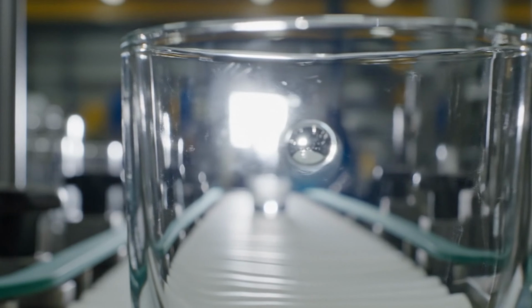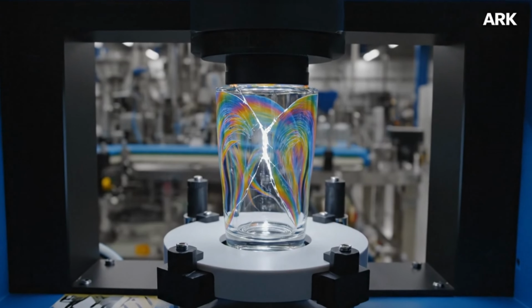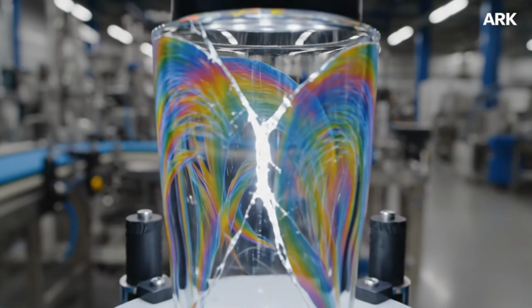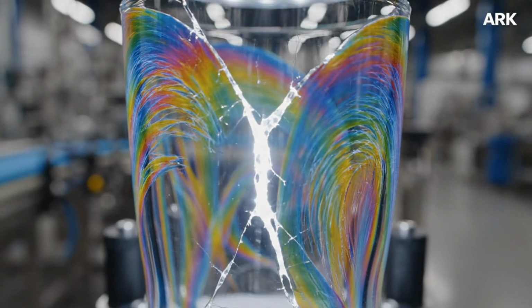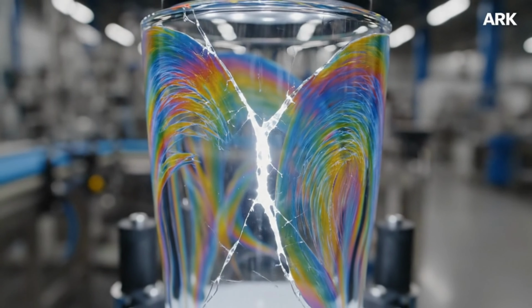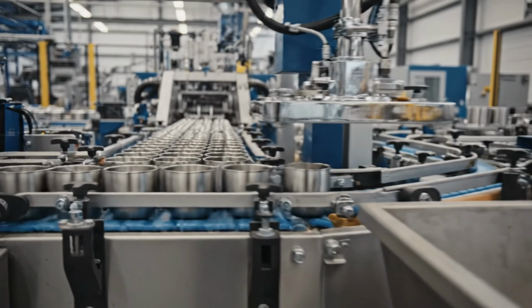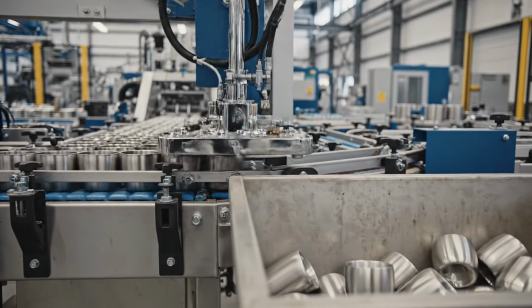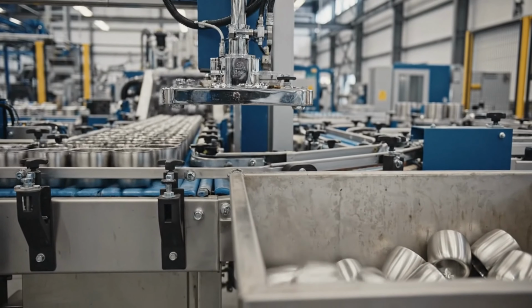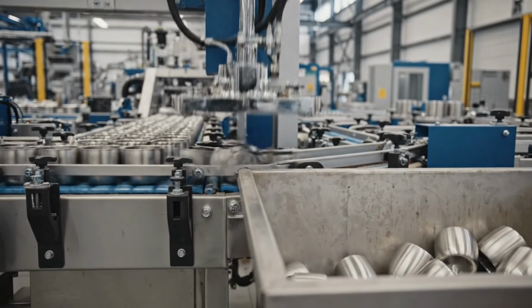This tiny air bubble, trapped during the cooling process, represents a critical quality defect. While beautiful through polarized light inspection, we can clearly see the birefringence caused by stress. The bright white indication confirms the presence of a crack in the tumbler. This is the reject mechanism in action. The pneumatic pusher arm swiftly removes any defective items.